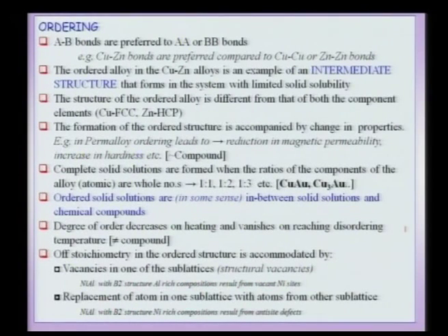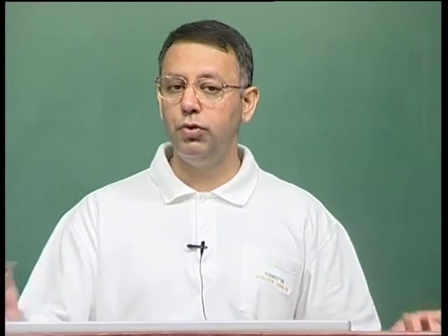But the important thing to be noted here is the asymmetry between going to the aluminum-rich side and going to the nickel-rich side. When I go to nickel-rich compositions, on the other hand, for instance Ni51Al49, then this results from anti-site defects. In other words, since I have more nickel, this nickel starts sitting in my aluminum sublattice. That means the aluminum sublattice cannot get fully ordered. What is a fully ordered aluminum sublattice? One wherein the whole aluminum sublattice is fully occupied by aluminum.